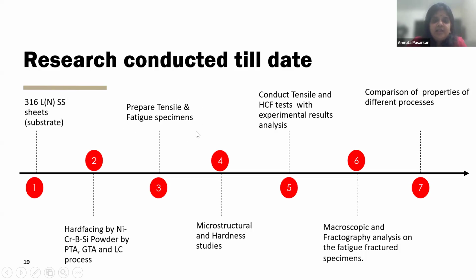Then I have prepared the tensile and the fatigue specimens, after which I have done the microstructural and hardness studies on these specimens to understand what the grain sizes are, if the proper hard facing is being done, and there is proper fusion between the two metals. Then the tensile and high cycle fatigue tests were conducted, and then the macroscopic and fractographic analysis was done on the fractured specimen to understand how the crack nucleation was there, how the cracks propagated, and basically the fatigue properties. The comparison of all the properties was done for the three processes.